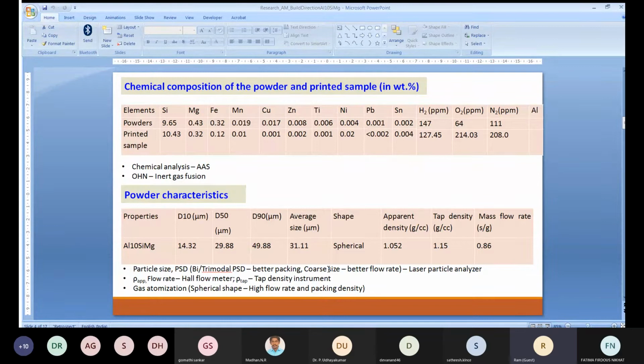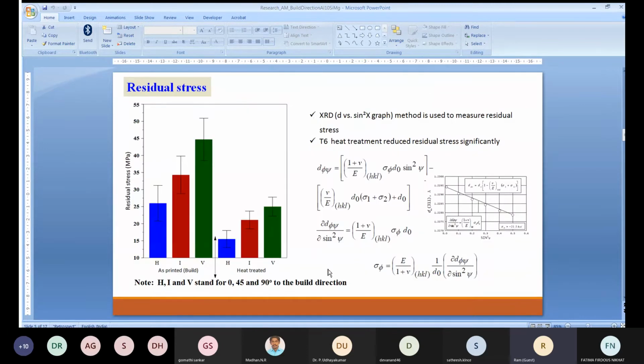which helps you measure the particle density after 1000 tappings. These particles were produced through gas atomization, because this is the one technique which gives you spherical shaped particles, which ensure high flow rate and packing density. Now let's see results one by one.